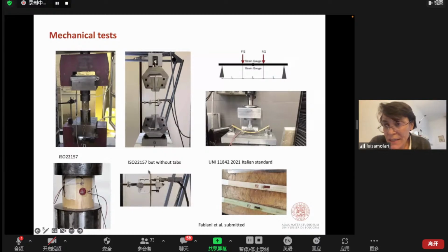Then we performed some mechanical tests to see how the treatment was influencing the mechanical performance. So we did compression test, tension test, and bending test. For the tension test and the compression test, we followed the ISO 22157, even if in the tension test we did not put the tabs to increase the cross section in the anchorage position.